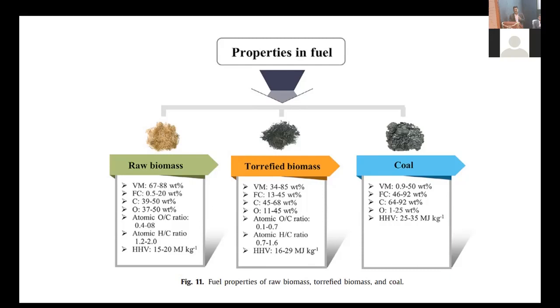If you are using normal pellets in stoves or something, there is no issue. But for pellets to be used in power plants, some qualities are required, especially moisture content. Moisture cannot be more than 10%. And also the ash content. That's why the government is telling us to use only 50% paddy straw and any other biomass to make the pellets. The government is coming up with a lot of policy, which is available on the Ministry of Power website.